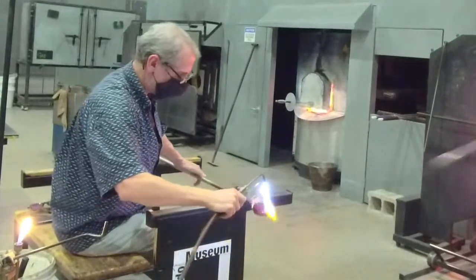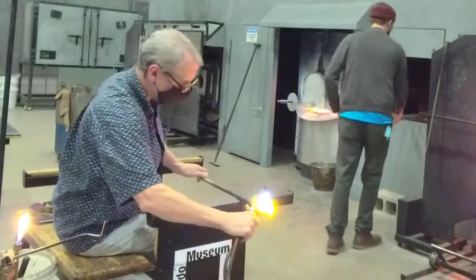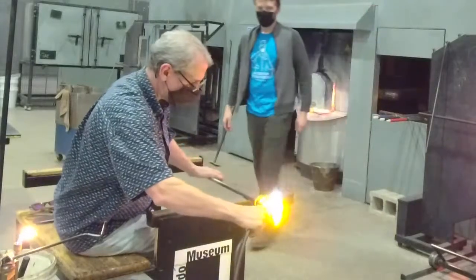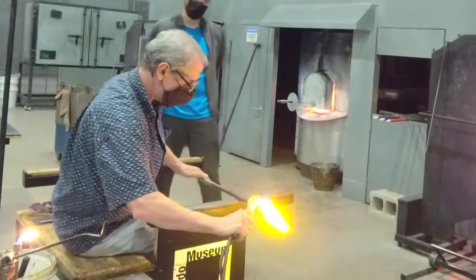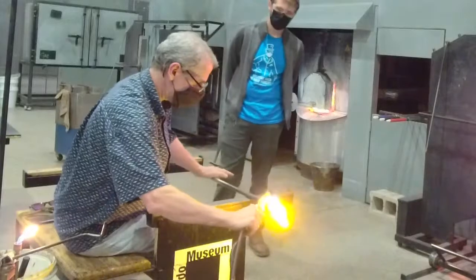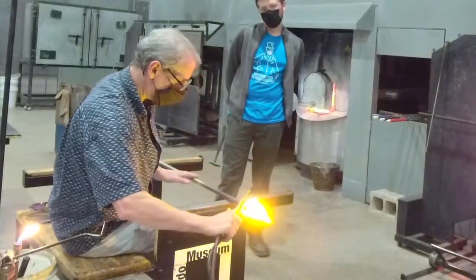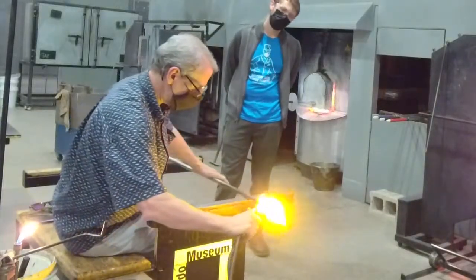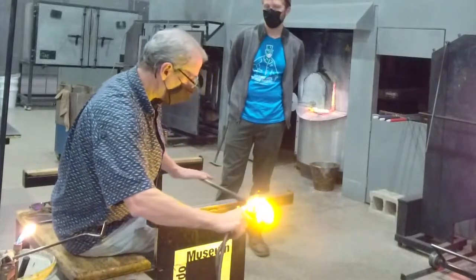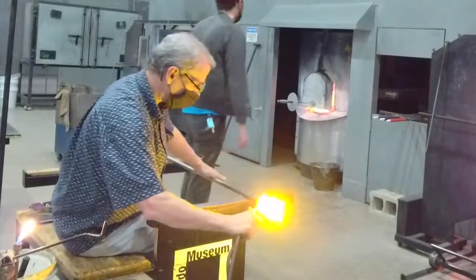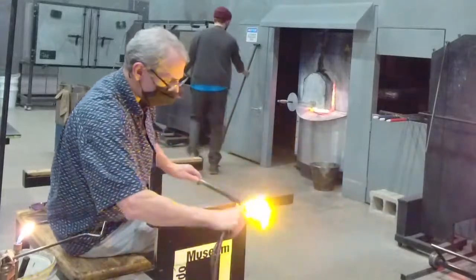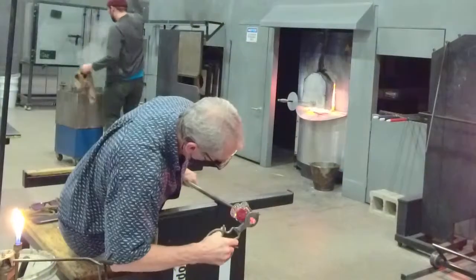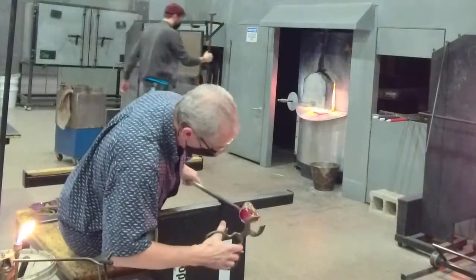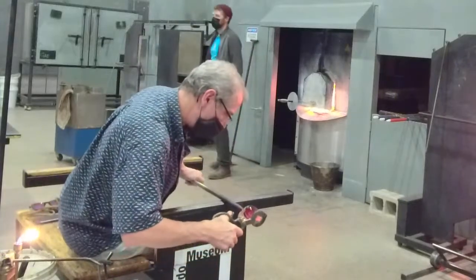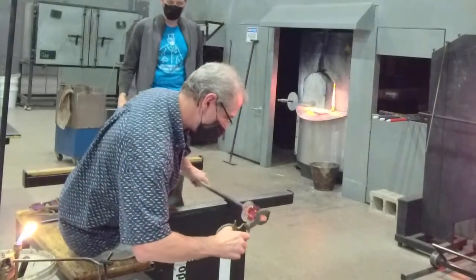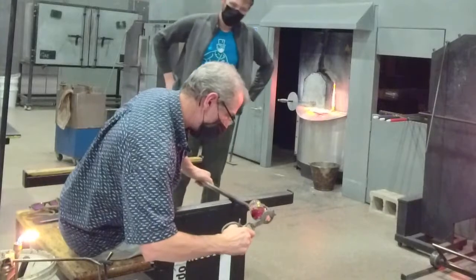I was using a very hot torch, it's a Ranger type. It's fueled by propane and oxygen. There's a premix inside of it, and the flame burns at about 3,500 degrees. And this flame is very important in sculpture, especially because it allows you to superheat a section. Otherwise you'll end up superheating the overall form, which could deform it. So that's why this torch is a specialized tool.